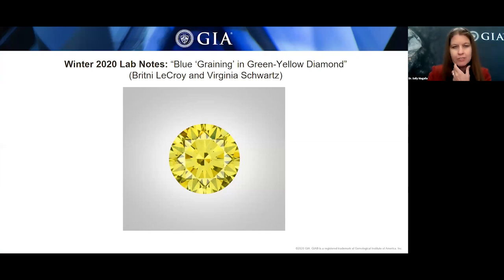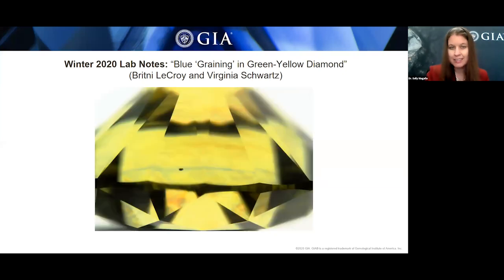The diamond was determined as a type 1aB, and it had distinct evidence in its spectroscopy of both high pressure, high temperature, and artificial irradiation. Under magnification, the stone showed strong green luminescence by fiber optic lighting. The next slide shows how it looked under the microscope under diffuse lighting. The stone had both yellow and brown graining, as well as some unusual blue graining.